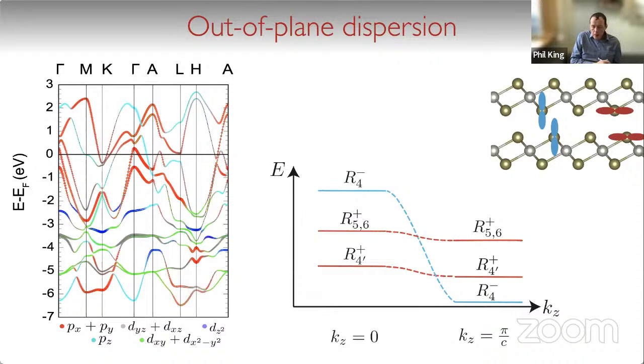Now, we also need to remember that we're dealing with a system where we have two chalcogens within the unit cell here, and so we're forming bonding and anti-bonding combinations of these. And this gives us an opportunity to have both even and odd parity states derived from these. And if you look at the parities of the states that you expect to have here, you can immediately see that actually these band crossings that we have as a function of the out-of-plane momentum are in fact band parity inversions in the system.